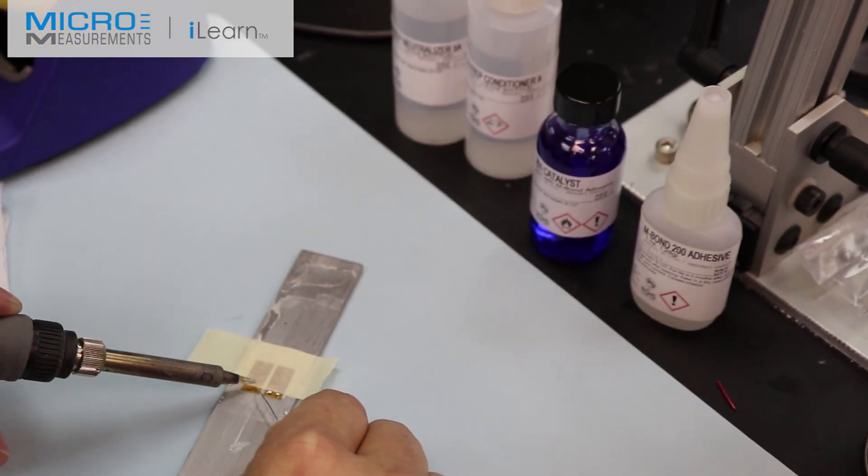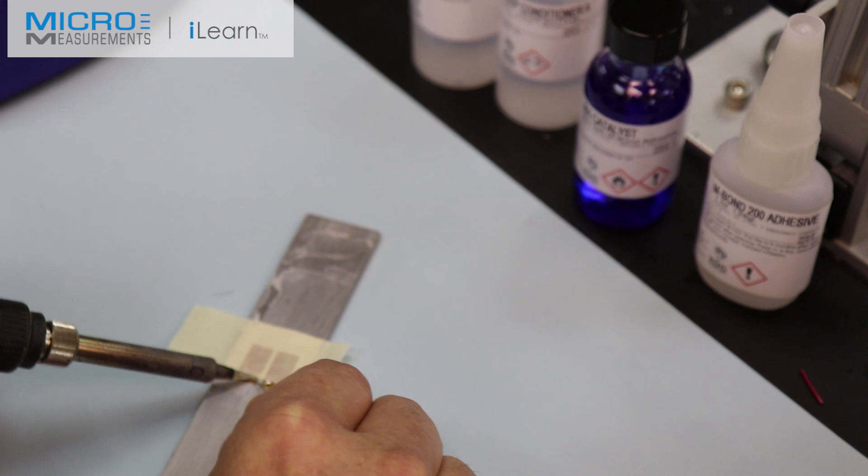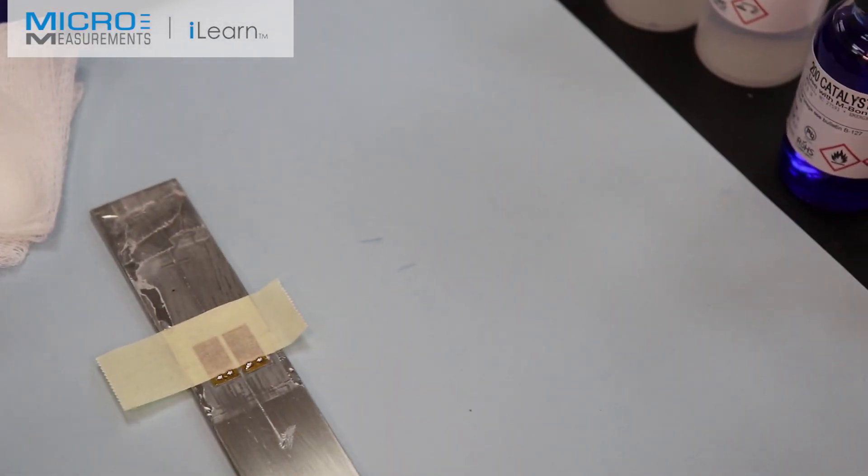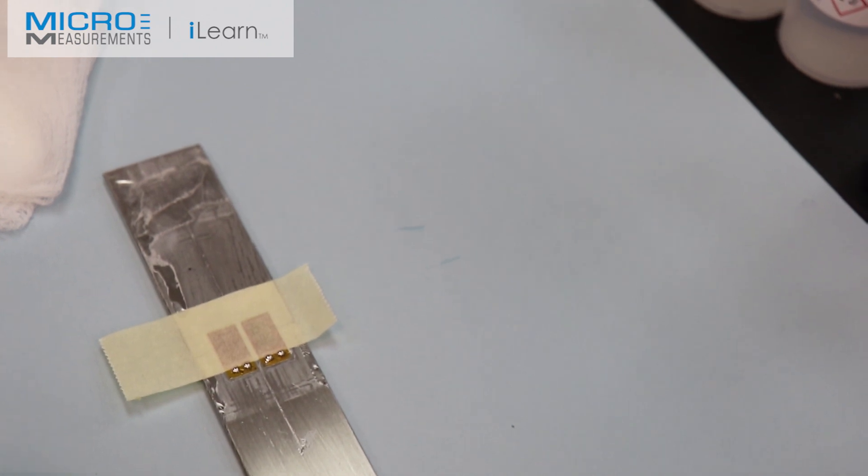Take the soldering tip. What I like to do is try to lay the solder right over top of the tab, and then press the iron through. Count one, count two, lift it up. And there you go. Now, once you've got those tinned, now you can focus on your wires.